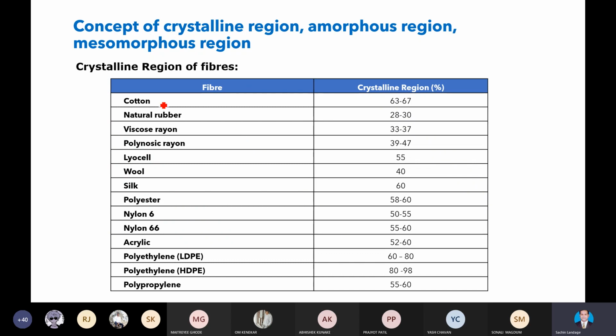If you see the crystallinity of the cotton fiber, it is 63 to 67%, natural rubber 28 to 30, viscose rayon 33 to 37, polynosic rayon 39 to 47, lyocell 55, wool 40, silk 60, polyester around 58 to 60, nylon 6 50 to 55, nylon 66 55 to 60, acrylic around 50 to 60, LDPE 60 to 80, HDPE 80 to 98, polypropylene around 55 to 60. Likewise, this is the crystalline region, and the amorphous region is 100 minus this. We will get the amorphous region.